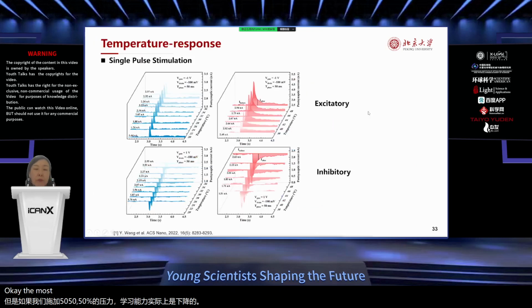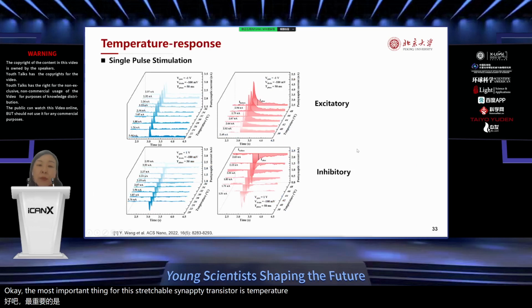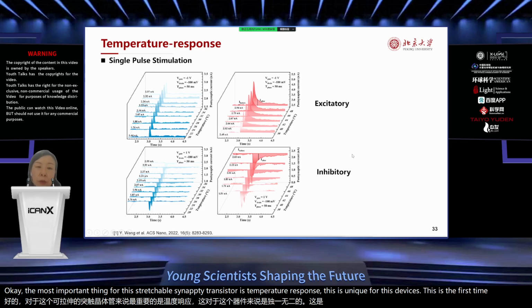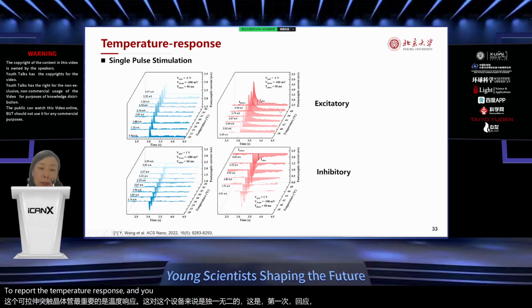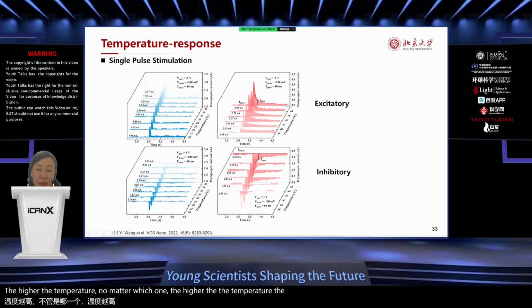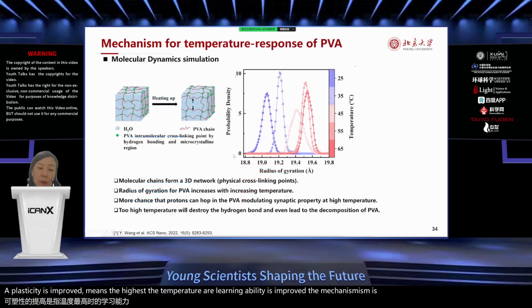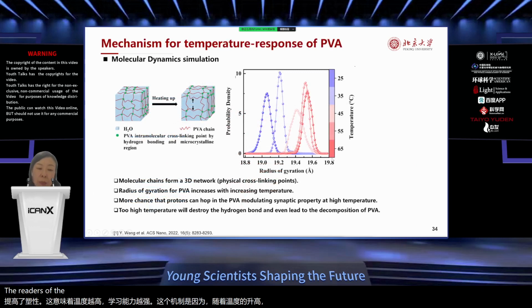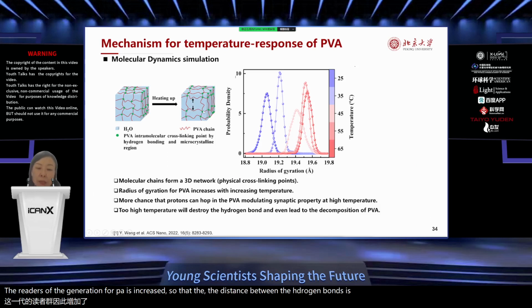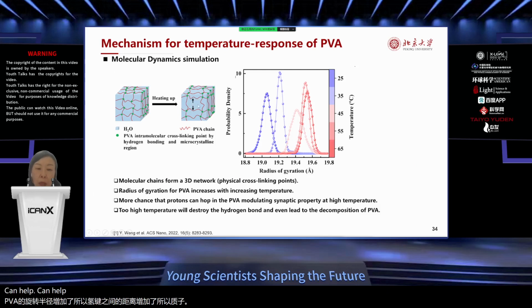Okay, the most important thing for this stretchable synaptic transistor is the temperature response. This is unique for this device. This is the first time to report the temperature response. And you can see from this excitatory or inhibitory performance that the higher the temperature, no matter which one, the plasticity is improved. That means the higher the temperature, the learning ability is improved. The mechanism is that with the temperature increasing, the radius of gyration for PVA is increased, so the distance between the hydrogen bonds is increased, so that the proton can hop longer and faster in this PVA material, so that the learning ability is increased.